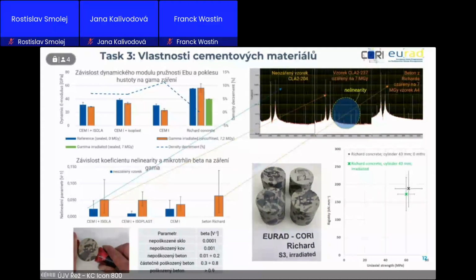Then we were testing Richard concrete. There are some small changes because some samples in the middle were not covered by aluminum foil, so it was a little bit different condition than the last sample, the green one, which was covered by the aluminum foil. Nevertheless, either way, there was no decrement of the density in the sample. The density is represented by the dashed line.